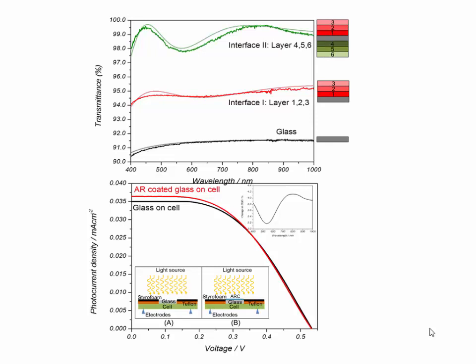And then we tried testing it on some solar cell. We didn't try to actually adhere the glass to the cell for this measurement, but we just set it on top of the silicon cell, and then we realized we are able to achieve like a 10% increase in the current. And then when we did EQE, we are able to see that the EQE spectrum actually reflects that of the UV-vis transmittance spectrum. So that proves that the current actually comes from that increased anti-reflection.